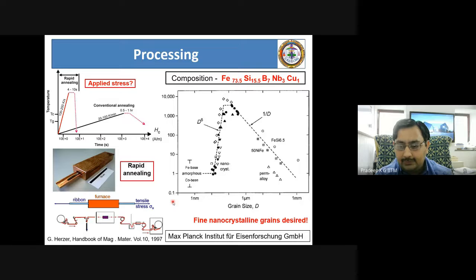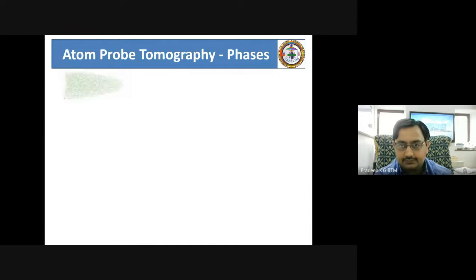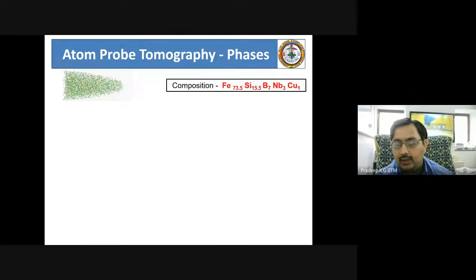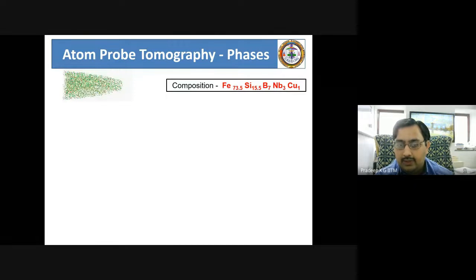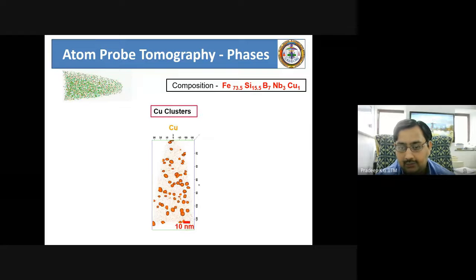Now when you do this, what we need to understand is the microstructure evolution, so that we can control the grain size to the nanometer range, so that we have a significant reduction in coercivity. So in order to achieve that, we need to use a tool like atom probe tomography. The material in the as produced state is going to be amorphous. That means all elements are going to be uniformly and homogeneously distributed. But if you now have them in an optimized annealed condition, then we are going to see 3 different phases.